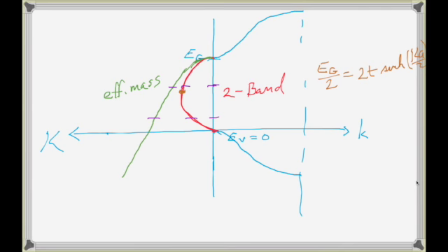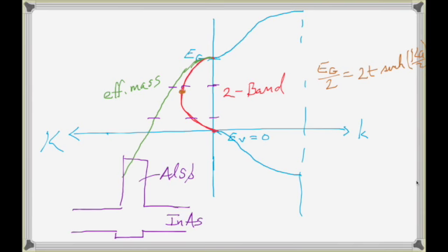They call that a stationary point in the tunneling problem. So if we look at what this means for the tunneling problem I originally drew, where we have our indium arsenide, now I'll draw both the conduction and valence band, our aluminum antimonide, and our indium arsenide. This is what the bands look like for this system. And this wrapping that I drew in red on the EK plot, if I superimpose it on this band diagram, wraps around like this.